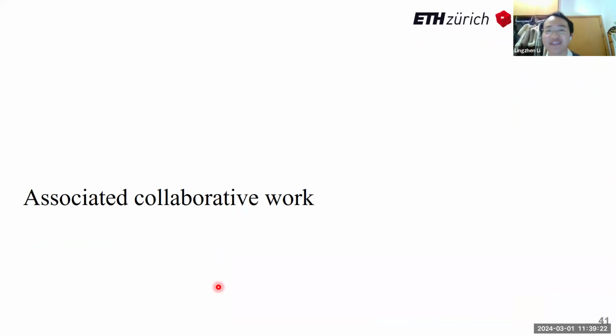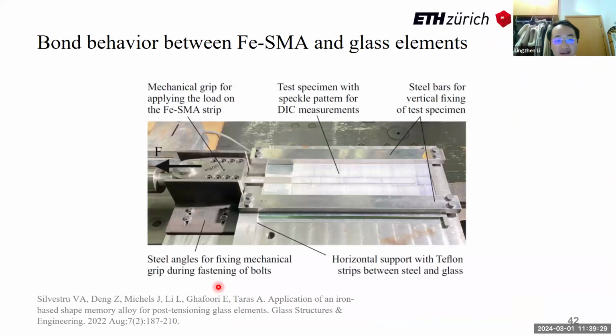Again, I guess I have some more minutes. It will be very quick, associated collaborative work. Collaborating with the steel research group at ETH Zurich, led by Professor Andreas Taras, we investigated the bond behavior between iron-based shape memory alloy and glass structure. We found that the bond behavior here is very similar to that between shape memory alloy and steel material.